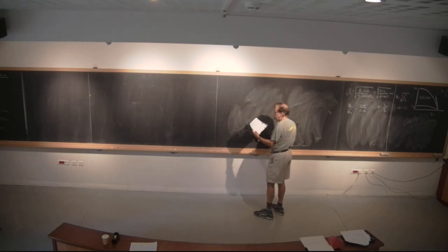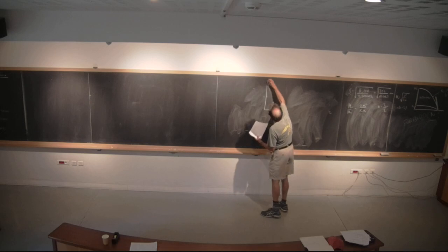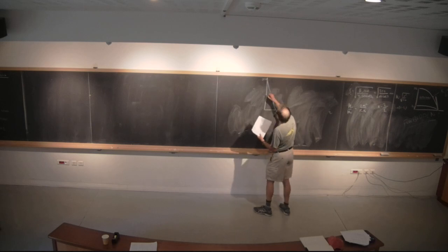uranium beryllium 13 is a 1 Kelvin superconductor. In fact, it's 1 Kelvin. It has a very, very high gradient here, and I forget what the upper critical field is, something like about 9 Tesla. But this thing extrapolates way up here and actually extrapolates to 25.7 Tesla. This is temperature, and this is mu naught H.